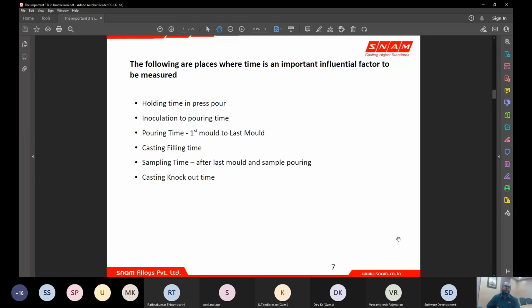So, casting pouring time. Next comes the pouring time. From the first mold till the last mold, this is measured as the efficiency of a foundry. How quickly you can fill a mold, and how long you will be able to pour with the treated liquid metal without losing its potency and still get good castings out of it is a challenge, and that depends on the foundry capacity and varies from foundry to foundry. It depends on various parameters like your method of pouring, your ladle capacity, your casting type, the bunch weight of the casting, the criticality of the casting, and the temperature control over the liquid metal.